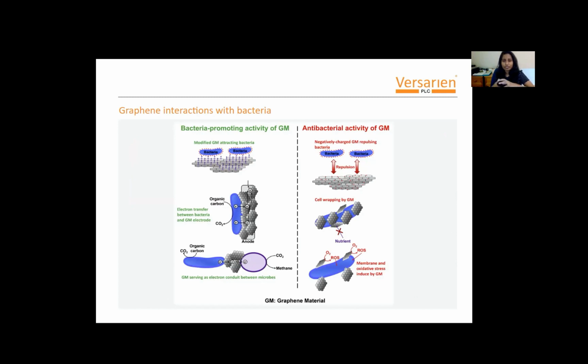Finally, going a little into the details of the mechanism, bactericidal activity from graphene can happen in a few different ways. If the graphene material surface is negatively charged, the negatively charged graphene material can repel the bacteria, so there is no effective adherence and attachment to the surface. Also, the graphene flakes can wrap the bacteria, preventing it from accessing nutrients. The other two mechanisms are membrane stress, that means damaging the cell membrane of the bacteria, and oxidative stress, releasing reactive oxygen species, which can disintegrate the internal cell structures.